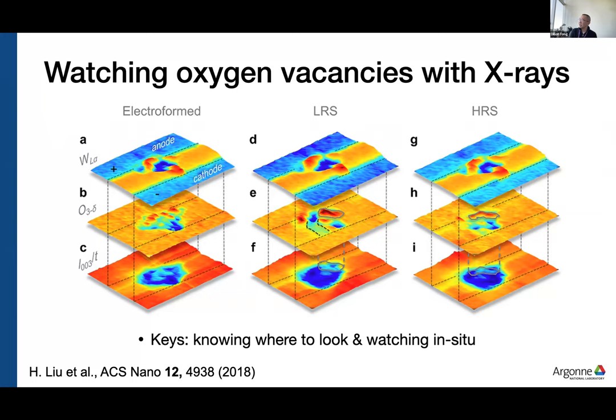In the low resistance state, which is the middle column, you can see that the oxygen vacancies have made a conducting path. And in the high resistance state on the right, you can see that the vacancy channel has now gone away. That's why it's a high resistance state. You can see all of this with X-rays, but you again have to do this in situ.